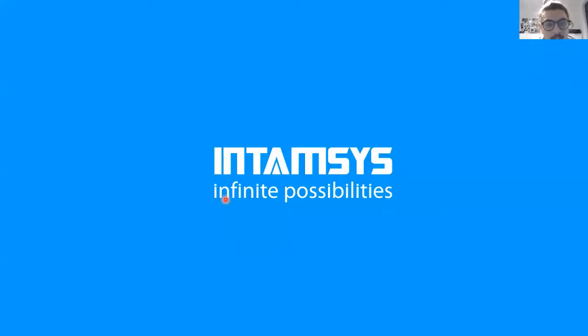We got another good question from Mike Block about geometry. It's hard to give a perfect recommendation on what kind of geometry is possible and what is not. What I could say is that with the 0.25 nozzle that we have for our machines, we can print wall sizes down to 0.5 or 0.75 millimeter. This depends a little bit on the requirements. Even thinner is possible, but then it gets less precise. It's a very good question, but there are more things than only wall sizes and holes. Holes themselves or cavities inside of the parts are, especially with amorphous printing, very manageable, while the material has a good overhang capability.